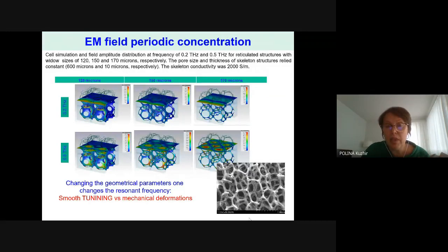It also allows us to concentrate electromagnetic waves periodically, and this concentration and the corresponding frequency will again be very dependent on the cell and window size. If you are able to change the dimension, like simple mechanical pressing, which is possible for graphene foams, you will immediately change the position of the absorption peak where you could concentrate the electromagnetic wave periodically.